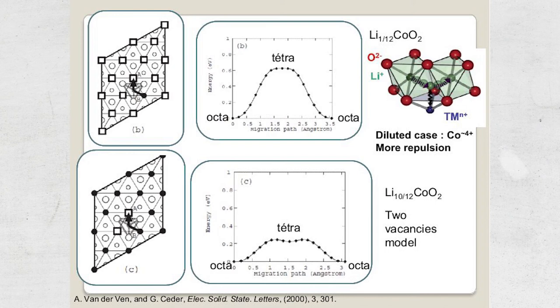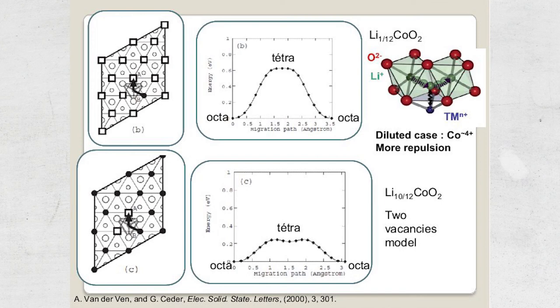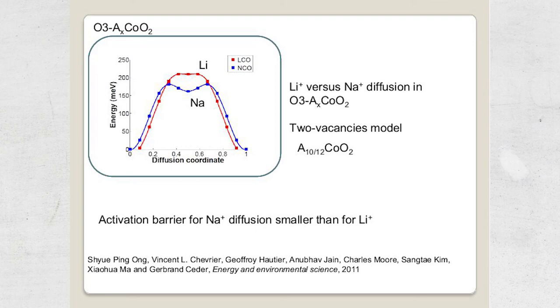This is because in the diluted case there is a lot of cobalt 4+ formed, and since the intermediate state is a tetrahedral site sharing a face with cobalt, we have a stronger electrostatic repulsion through this common face, making this site less stable. This study was further extended to compare the diffusion activation barrier between lithium and sodium.